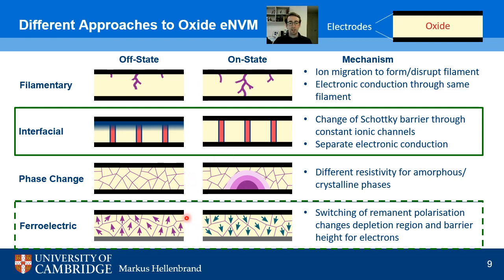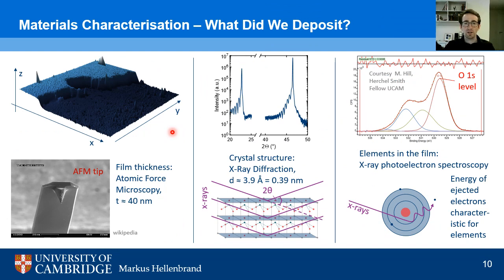And finally, another example, these are not all of the approaches being followed, but one that we are investigating as well in our lab, but which I will not talk about more today, is based on ferroelectricity. So this is a materials property where polarization inside the oxide can point in different directions, so either up or down. And the direction of this property, called polarization, also determines the height of the energy barrier. So think of the slide before. If the polarization points in one direction, the energy barrier for the electrons is high. If it points in the other direction, the energy barrier is low. And once again, we can represent our two binary states that we need for storing information in a computer, state 0 and state 1.